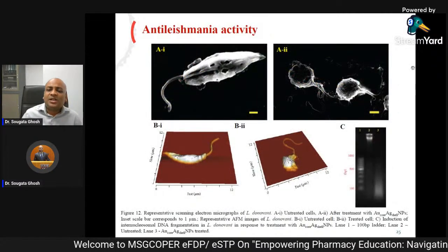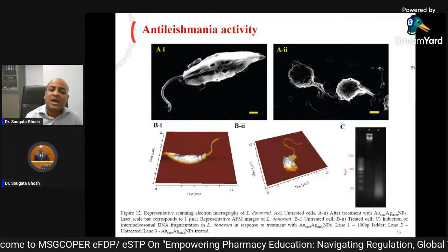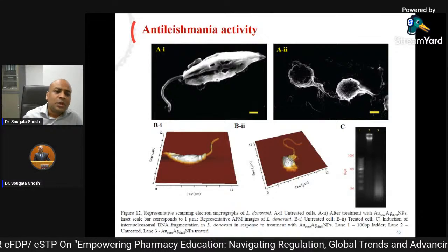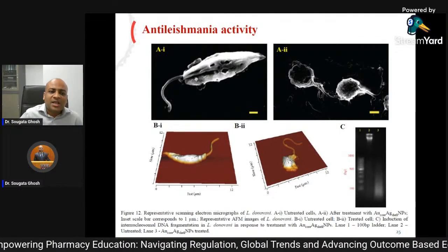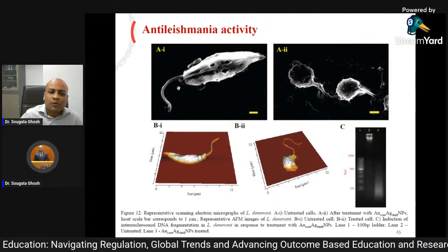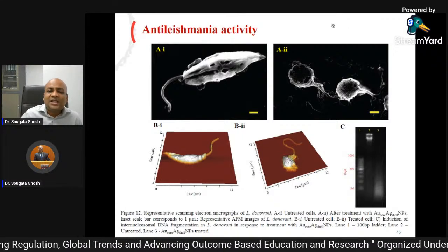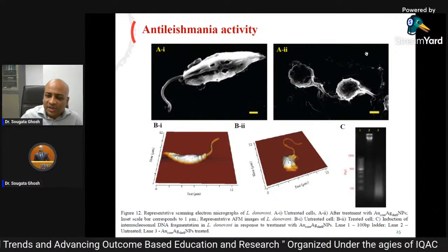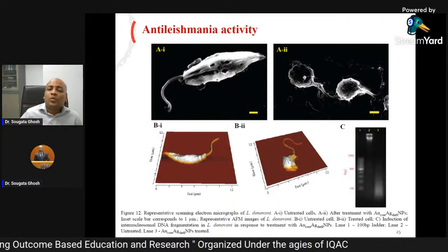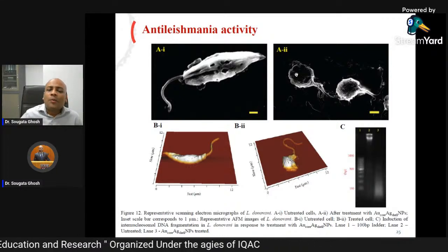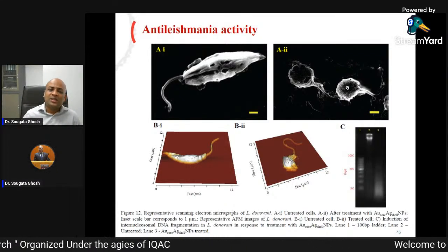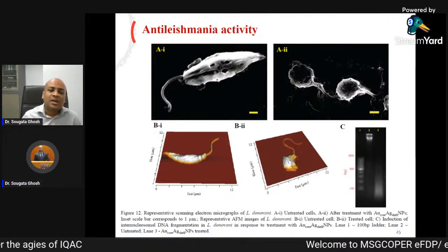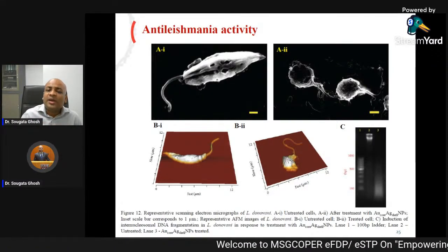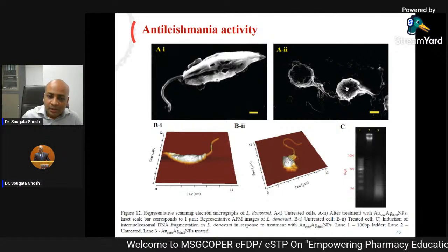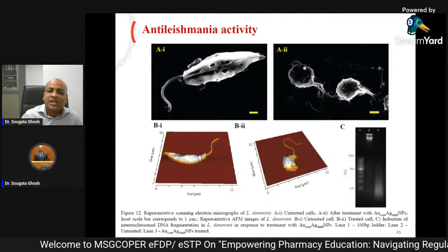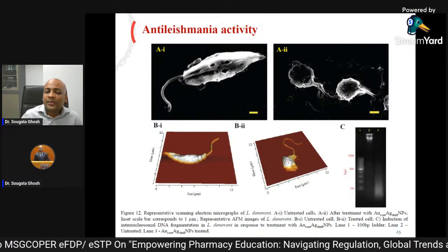Now we checked another disease called Leishmaniasis or Kala Azar. Leishmania donovani is the causative agent. This is the Leishmania donovani cell. When we reacted with our gold core silver shell nanoparticle for 24 hours, there is complete breakdown of the cytoskeleton. The entire cell was crippled. There was breakdown of the cytoskeleton and it becomes spherical in shape. You see, this is a spindle shape and this is a spherical shape.